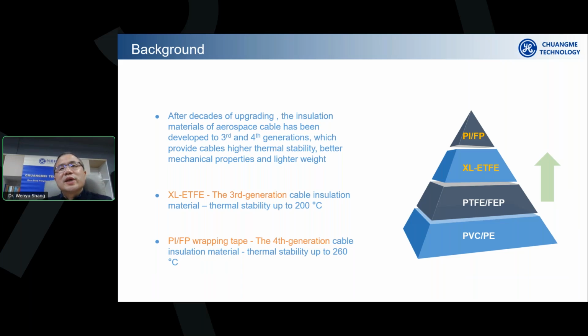And then, in the past few decades, as airplanes got faster and more modern, the insulation material temperature demand started to surpass 200 and even rise to 260, 280 degrees C levels. So that called for the third generation, like the XL-ETFE, and the fourth generation, like the polymer plus fluorine polymer composite sheet, composite film, as the insulation layer to sustain such a high-temperature working environment.